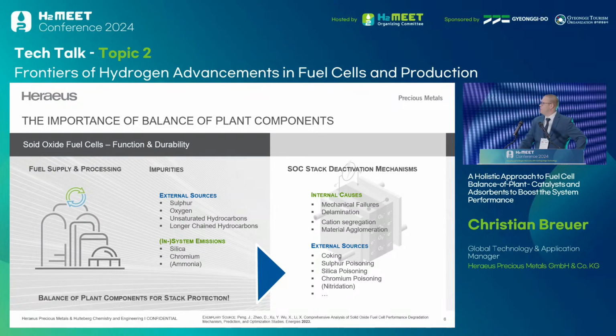And then we look again at the sources. Once again, there are fully external sources for these poisons, like sulfur, oxygen, unsaturated hydrocarbons, and longer chain hydrocarbons that all could cause trouble in the stack operation. And then there are also in-system emissions like silica or chromium that can get into the stack and cause troubles in operation, especially with regards to durability. And this is where we set on with the balance of plant components.